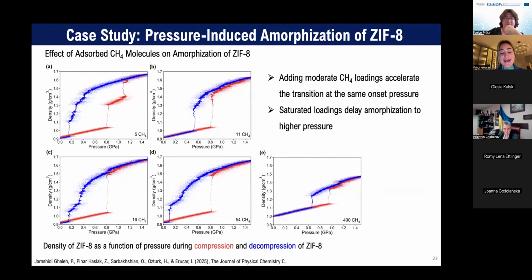Here you can also see we have adsorbed methane. Imagine that you have gas molecules inside your structure and you want to do amorphization with these gas molecules. What is happening? You have, for example, methane molecules inside your structure. Here you can see different numbers of methane molecules available inside ZIF-8, and we do amorphization with these gas molecules. 400 methane is the saturated methane loading for ZIF-8, and in order to identify this number of molecules, we initially performed grand canonical Monte Carlo simulations. We find that when you have saturated loadings, this can delay amorphization to higher pressure.